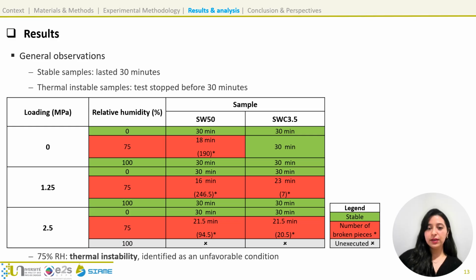Stable samples shown in green resisted for the full 30 minutes, which represents the test duration, while unstable samples shown in red failed earlier when the bricks could no longer withstand the applied load. In addition to the duration, the table also reports the number of broken pieces larger than 10 millimeters after sieving. What clearly emerges from this result is that the 75% relative humidity condition is the most unfavorable one, as it's the only case where instabilities occurred. By contrast, under both 0% and 100% relative humidity, the two types of brick showed consistent resistance across all loading levels.